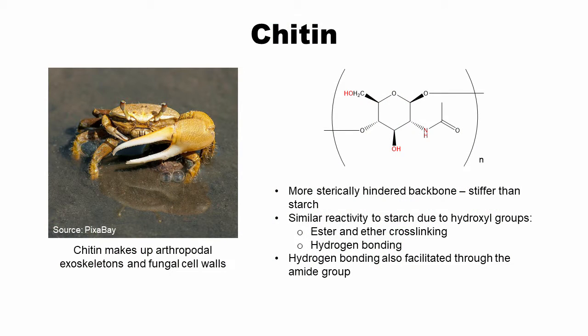Chitin is another promising biologically sourced filler. It is also a polysaccharide that often plays a structural role in arthropodal and insect exoskeletons and fungal cell walls. The N-acetylamide group increases backbone steric hindrance and therefore the backbone stiffness. It has similar reactivity and ability to be a hydrogen bond donor and acceptor as starch due to the presence of hydroxyl groups. In addition, its ability to form hydrogen bonds is facilitated through the amide group.